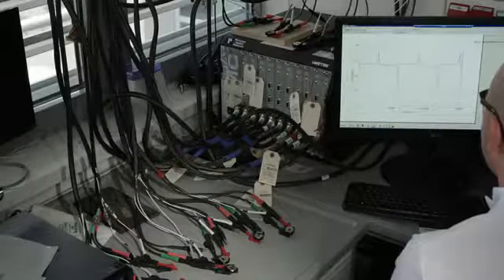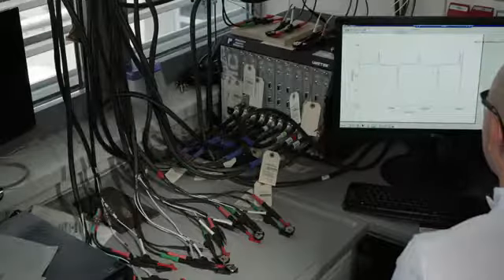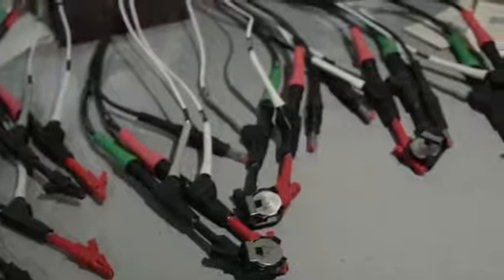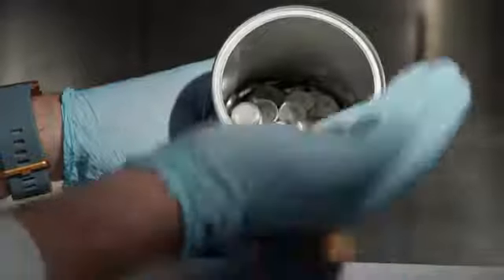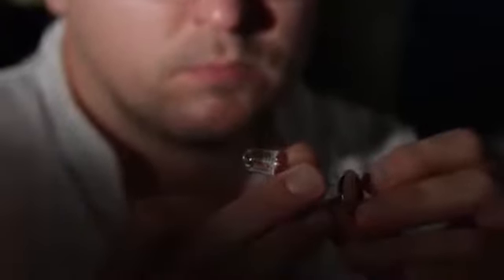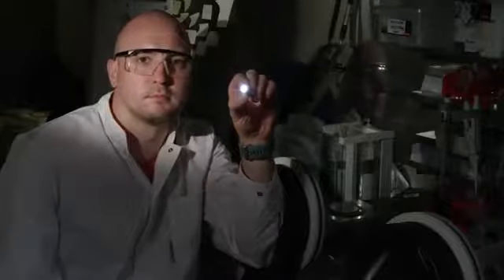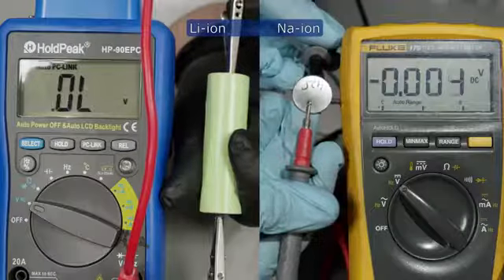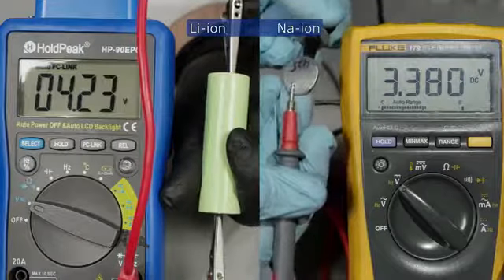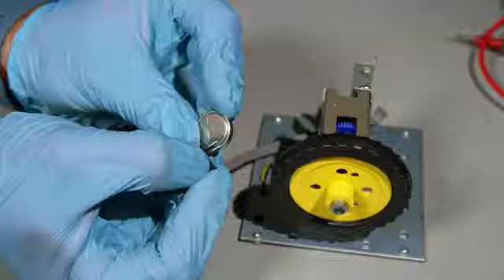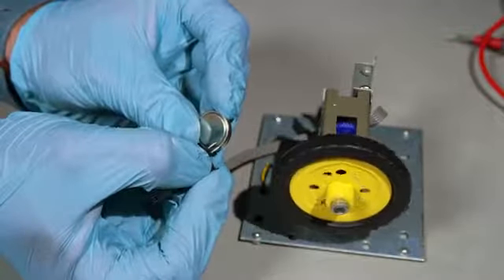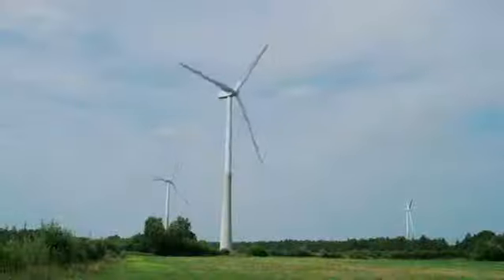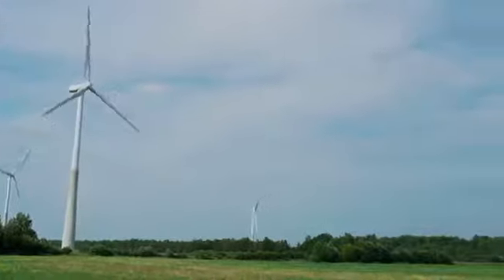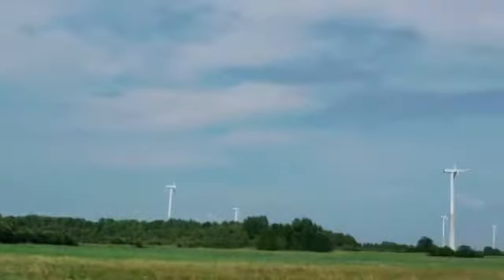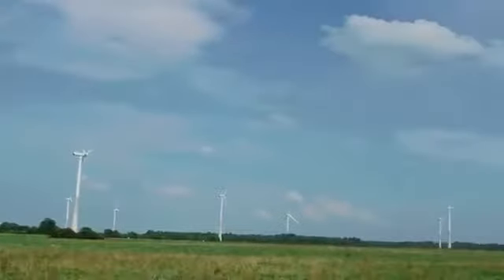The cell operates at 3.4 volts and a lot of them had to be tested. It can easily light a white LED light. However, this is only a small prototype and it's relatively new technology. However, sodium-ion battery cell has 20% lower voltage, which leads to lower energy density than lithium-ion batteries. The reason for developing sodium-ion batteries is that sodium is more abundant and a lot cheaper than lithium.